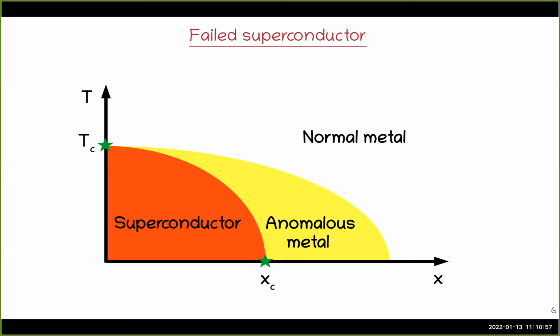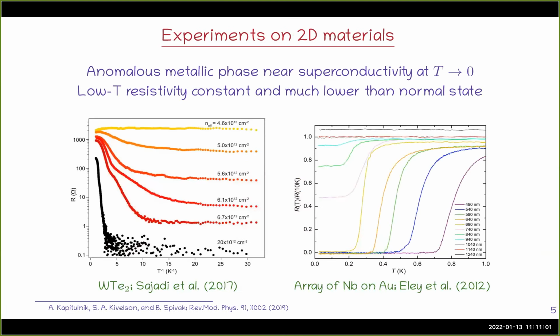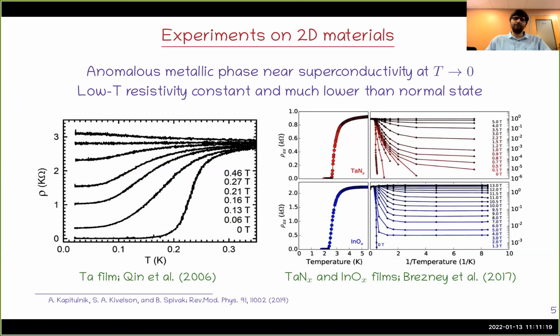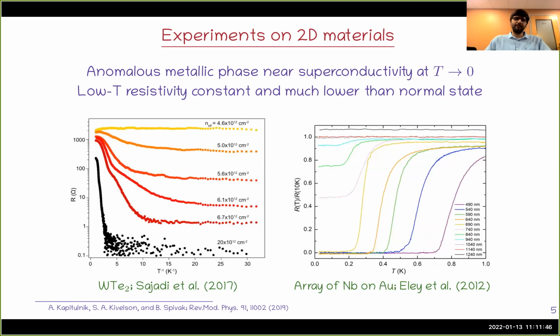So I was asking what will be some actual numbers of the saturated resistance that you showed in these plots? The typical numbers of resistance, what will they be? So it depends on the material. For example, for this WTe2 material, the resistance is like 10 ohms or something, whereas for certain other examples it can be much higher, like 1 kilo ohm. What is interesting here is, rather than the absolute value of this saturation, you should compare the ratio of the saturated value to the normal one. In certain cases it can be as high as an order of magnitude or 2 orders of magnitude higher. So here it's a ratio of 3 or 4, but in this case the ratio is like 1,000. Here it's of the order of 1, here it's of the order of 1,000, so 3 orders of magnitude. So it really depends. And that's something very surprising, that there's a very drastic change, very high conductivity, but not yet superconducting.